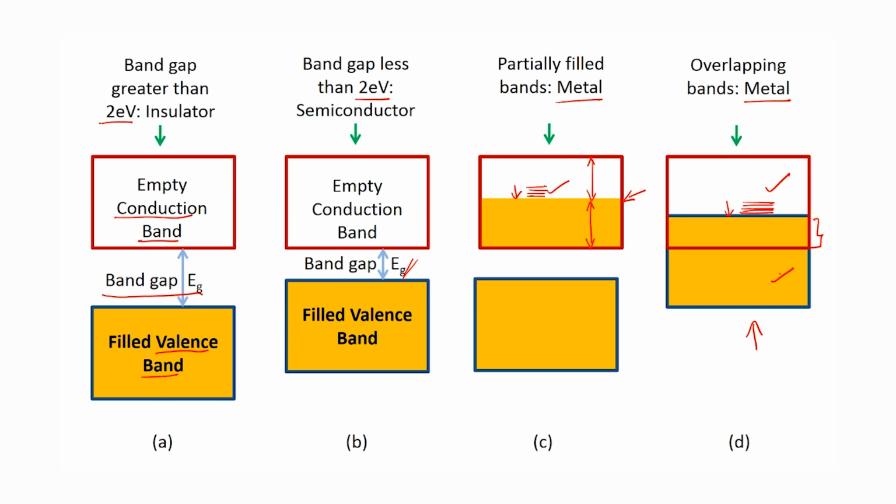This is very critical to the behavior that metals display. Since there is no gap, the electrons at the top of this level are able to occupy energy levels immediately above them very easily. In semiconductors and insulators, immediately above the topmost occupied level there is a forbidden gap, and that gap is fairly large, several electron volts. Whereas in the metal you have virtually no gap; it is a continuous set of energy levels just above the highest occupied energy level.